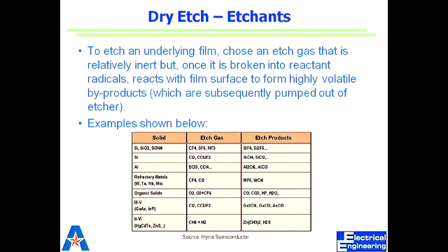That is energetic fluorine or fluorine ions. I would say this is the first product that forms. When more fluorine ions react with that, we get to this form. So initially SiF2 is formed. So the answer is that only these two are the volatile gases, in gaseous form, and they can be carried away by the gases.